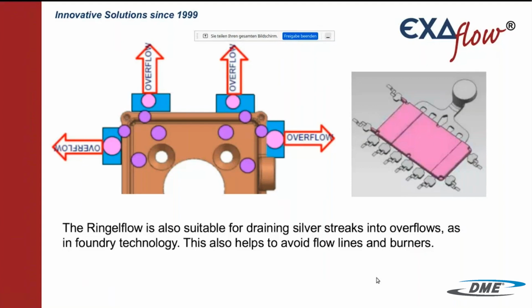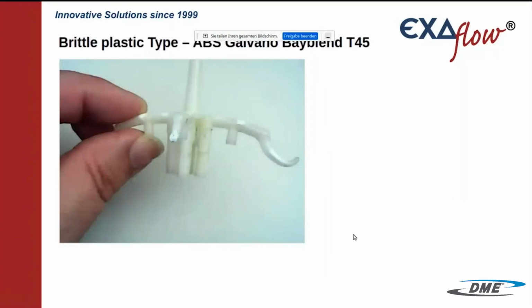It also helps to avoid flow lines and burners. So then you do not have only to inject the plastic in one Ringelflow. At the end of the part, you can produce overflows or add overflows to solve such problems. Here we see a brittle plastic type. It's an ABS blend, and the white shiny spots here, if 10% more, it will break, but we see only these shiny spots, but it works. It never breaks, and so 100% sure safe production. And as you can see, if the plastic is brittle, you can have such a result.